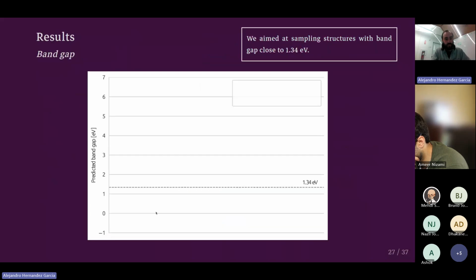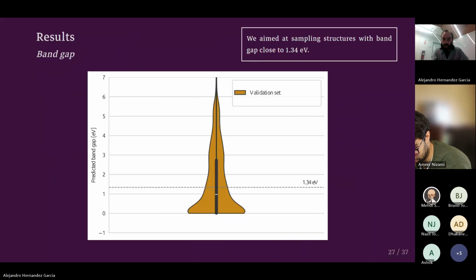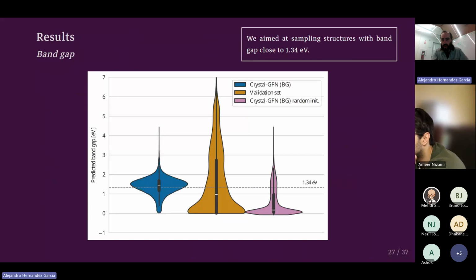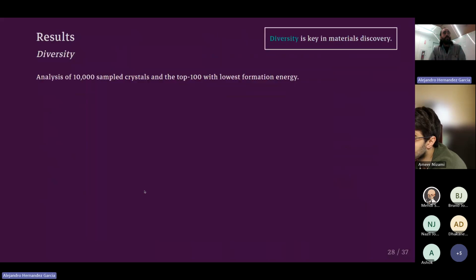We did very quickly something similar for the band gap, except that here we don't want the lower the better. We wanted to have values close to a target band gap of 1.34 eV. Again, this is the validation set. This is the random distribution, and this is the distribution we get after training. So again, good news because we get a distribution centered around the target value. So this is essentially showing that it is doing what we want it to do. And in terms of diversity, which I've been arguing is very important, I think I'll show this and then stop. Is there a question?